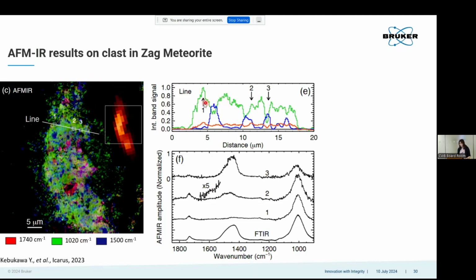And then you see that you have these areas where the silicate is high and also the carbonate is high. You see areas where the silicate is lower and that you have more of these PAH materials. So you're really seeing the sequestration of the smaller domains within the meteorite. And so this is giving you information on how these meteors are formed and how they're all compressed together. The really impressive thing for the researchers, again, was looking at the relationship between the AFM-IR result and what they get through FTIR, where you're measuring this whole material.